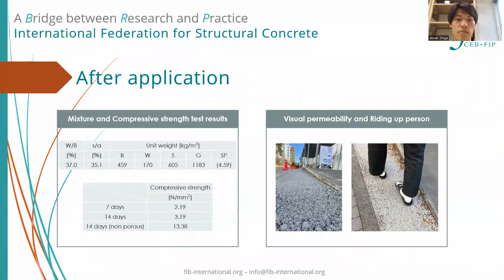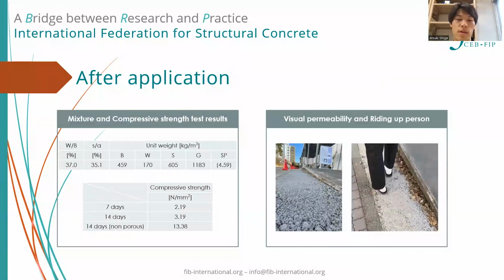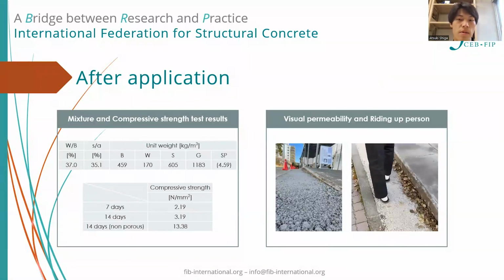Compressive strength tests were performed on the produced concrete. The results showed higher results compared to the laboratory tests, and the difference before and after the granulation was about 1/4. However, the fact that on the next day the material could be worked on and at the same time the permeability was confirmed suggests results were not affected by the low measured value.